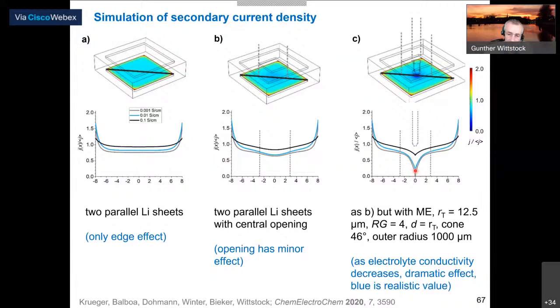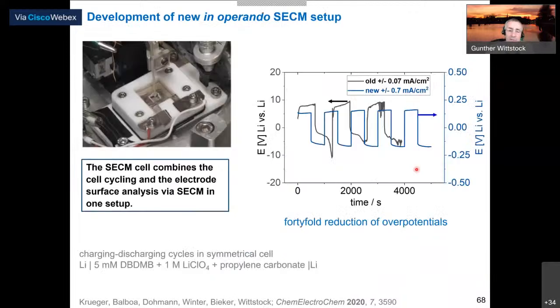So what we have to do is intermittently retract the electrode, do the charging discharging, engage the electrode again and continue. But that can be done with rather good reproducibility. So when we do that, now we have a cell where we can really record reasonable charging discharging curves for a lithium electrode. We could reduce the overpotentials by a factor of 40 in that SECM cell. So we can now really follow the lifetime of such a lithium electrode in that cell.